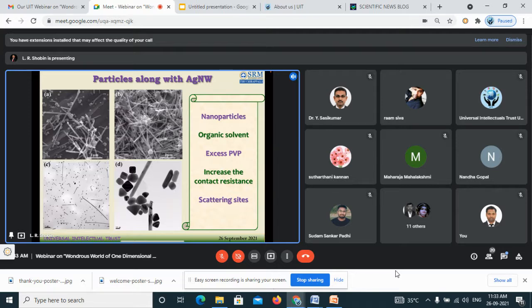So what are all the unwanted things you have to remove? First one is the nanoparticles. If you have glycerol, an organic solvent, that you have to remove. There will be some excess PVP, which will reduce your conductivity, that you have to remove. And if these three components are present, what will happen? It will increase your contact resistance. These particles will act as scattering sites actually. If you pass light, it will scatter. Light will come here, hit over here, and it will scatter. So whatever it costs, you have to remove these particles out of the system.